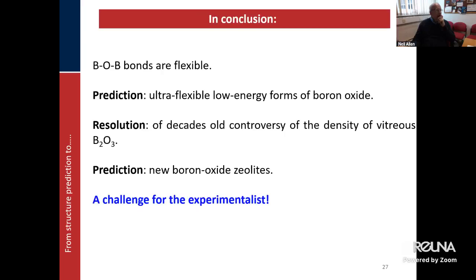So that's our conclusion, that we've built in some chemistry about the flexibility of the BOB bonds to predict new forms of boron oxide. It solves this old problem about the density, but for me the interesting challenge is to see whether someone could construct zeolites based not on silicon but on boron. Now, I know zeolite synthesis is a very specialist thing. That's what people do, that's their career. When I worked with a big company, we had somebody doing that. So that's a huge challenge.